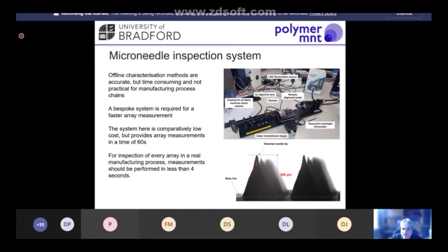They take too long. Basically, to measure a microneedle array using one of these systems is going to take tens of minutes or hours, when what we need is something that sits within our manufacturing system and can measure every few seconds. So we've explored this. We made a bespoke measurement system using a telecentric illuminator and a telecentric microscope objective to measure each of the needles on a 10 by 10 microneedle array.